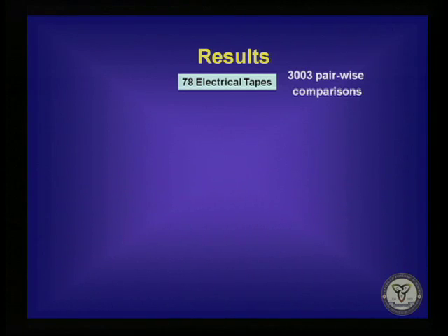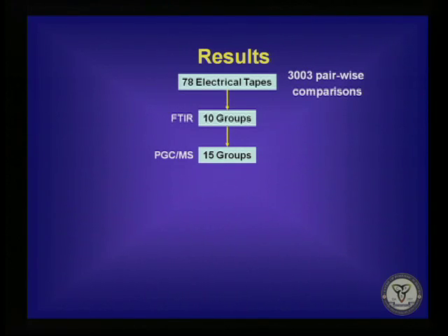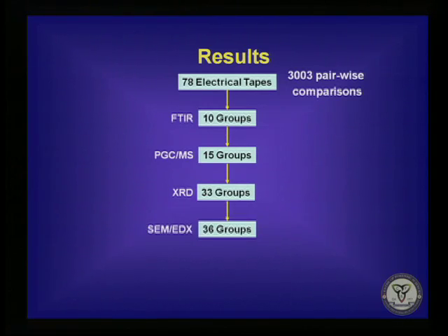Our results for the 78 electrical tapes analyzed, which represents 3,003 pairs: we first grouped those tapes into 10 groups according to FTIR. We then compared each of the tapes within those 10 groups, and we looked at the PGC-MS results for the tapes within each of those 10 groups. And we were able to further break those 10 groups down into 15 groups. We then looked at each of the tapes in those 15 groups, and we looked at the XRD results of those groups, and we were able to further break those 15 groups down into 33 groups. And then we looked at the elemental composition from SEM-EDX of each of the 33 groups, and we were able to break that down into another 36 groups.